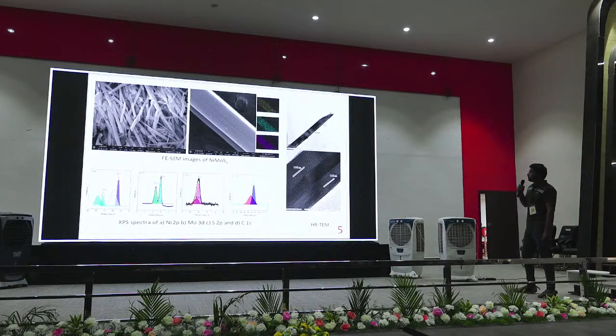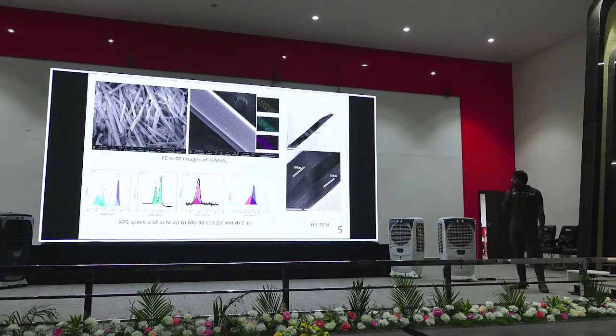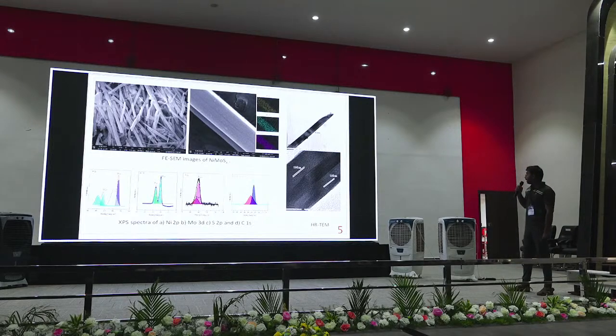F is the same image of nickel molybdenum sulfide, and below are the XPS spectra: nickel 2p, Mo 3d, S 2p and carbon 1s. This is a TEM image. Nickel sulfide usually attains d-spacing of 0.24 nanometer, whereas molybdenum sulfide 0.62 nanometer. Here we obtained d-spacing of 0.648 nanometer. This difference is because nickel sulfide was doped inside. Above, we can see the fine image of a nanobar.